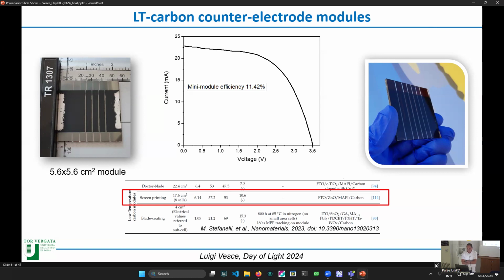The efficiency is 11.4%. And if we compare with something present in literature by screen printing, we are almost on the right way. Here it is a little bit higher, but they use blade coating for the carbon, which means that they put a tape by hand on the module, deposit carbon, and then remove the tape. So it's something that yes, you can do in your lab, but if you want to present something that is scalable and transferable to the industry, it is not so good.